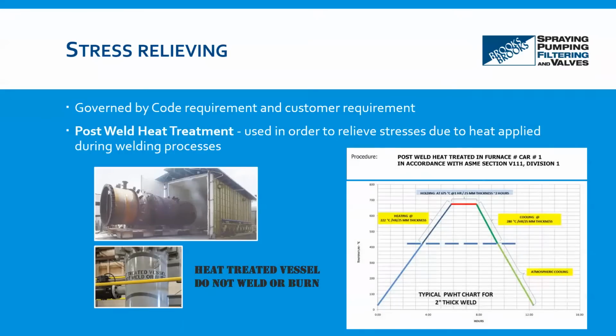Thanks, Nico. Again, in ASME code, Section 8, Division 1, there are a lot of conditions which cause the post-weld heat treatment to be mandatory. Like in Section UW-2, when your service is lethal, or it is an unfired steam boiler, or a vessel is subject to direct firing, and your material is carbon steel or low alloy steel.